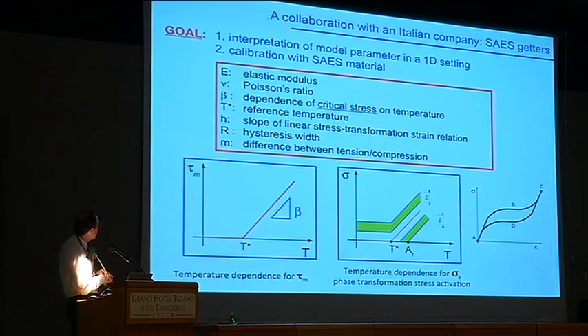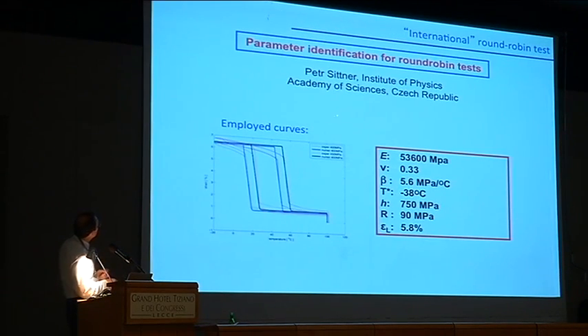Beta is the dependency of this slope with temperature, so it tells you how the material changes with temperature, and then, for example, H gives you a measure of the slope of this phase transformation region, and R gives you a measure of the width of this region, so of the width of the hysteresis region, and M is a quantity which describes the difference between tension and compression. So very few parameters that in any case need to be calibrated. And when you want to calibrate, we start to calibrate. Here the picture doesn't look too great, but basically we always use a strain temperature diagram, which is the basic diagram used by companies to test actuators.